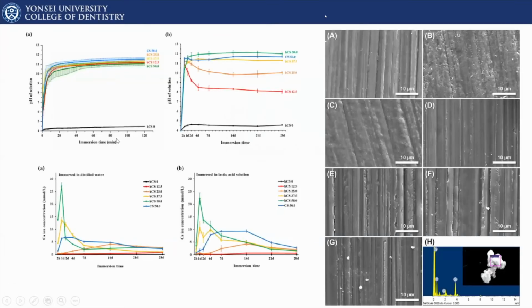So as I said earlier, it provides an alkaline pH. When they are in acidic conditions, like pH 4, it dramatically increases the pH to neutral or even alkaline environment, and this is relatively maintained for a longer period when a high amount of the hydrated calcium silicate has been added.